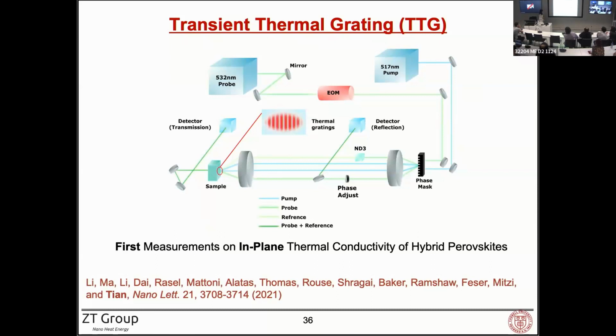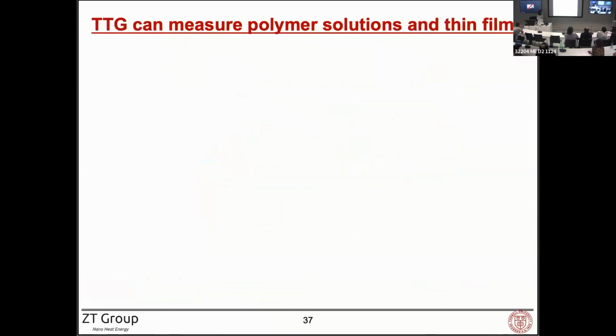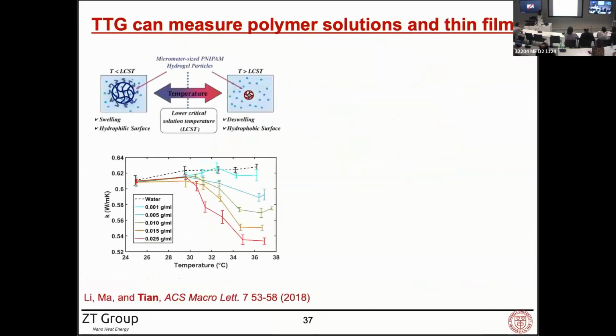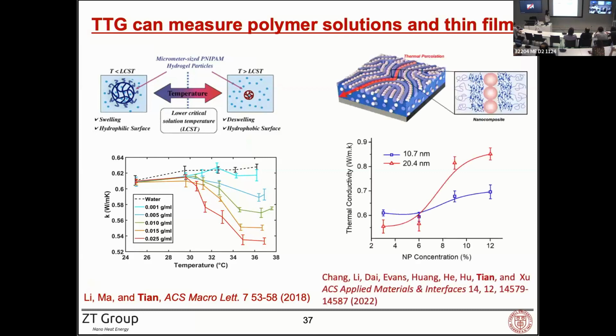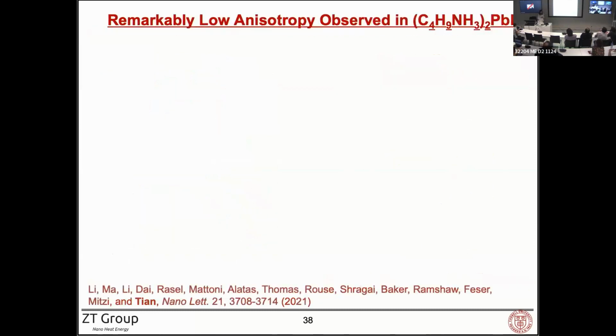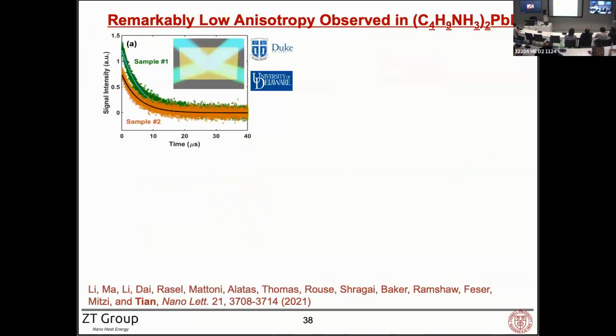So with that, we're able to perform the first measurement of the in-plane conductivity of hybrid perovskites. And this can also be used to measure polymer solutions, where we demonstrated this for thermoresponsive polymers, where we can see the fast conductivity change across the lower critical solution temperature. It can be used to measure polymer thin films, where we measured supramolecular thin films and observed thermal percolation behavior at a lower concentration. So coming back to the 2D hybrids, we obtained the samples from two independent groups just to cross-check our results.